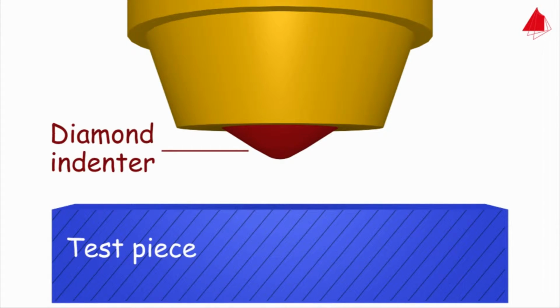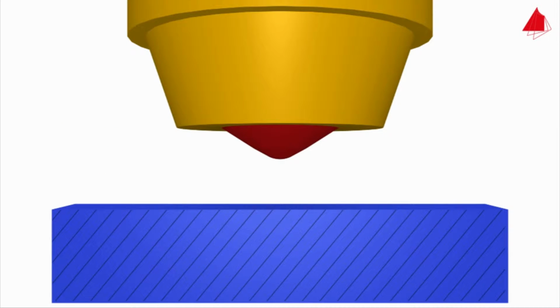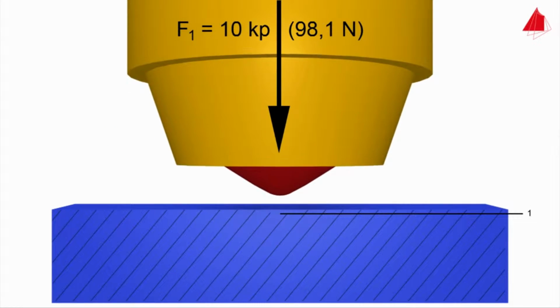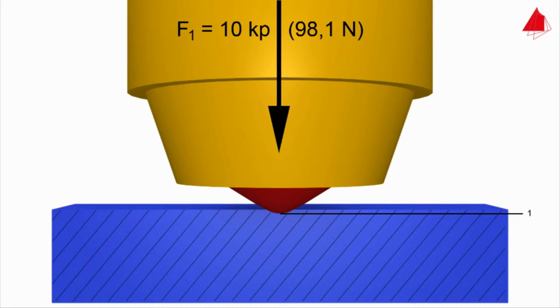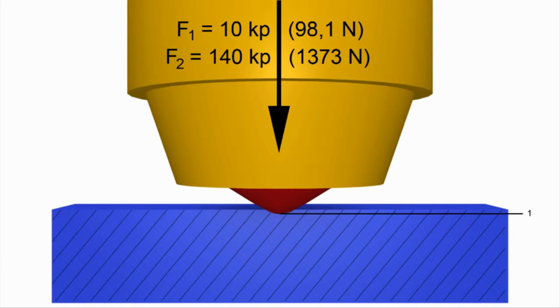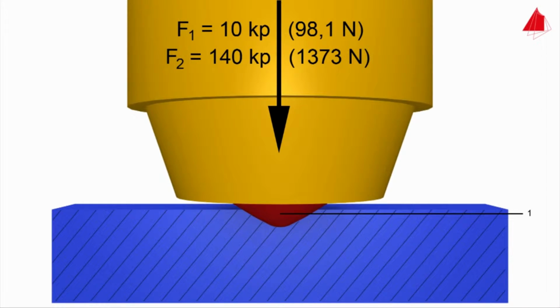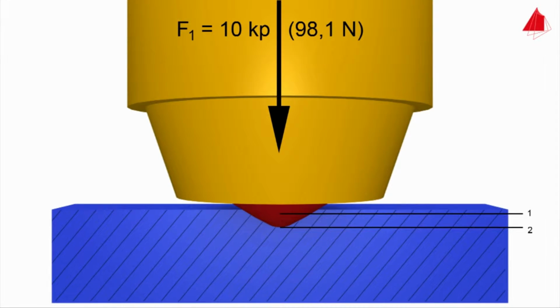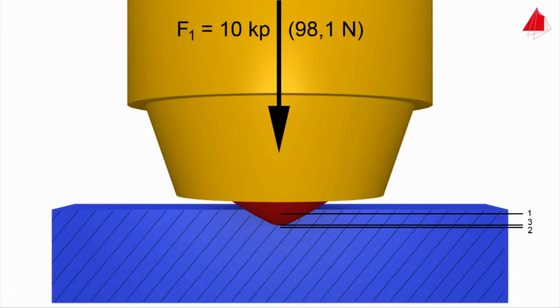In step 1, the diamond cone is pressed onto the test piece surface with a minor force of 10 kiloponds. The depth of indentation under this preliminary load is the reference point. In step 2, the test force is increased by 140 kiloponds, which is acting as the major force. This means that an overall force of 150 kiloponds is now acting on the indenter, and this force is held for a certain time. In step 3, the major force is removed again. While the minor force is still acting, the permanent increase in depth of indentation E is measured.